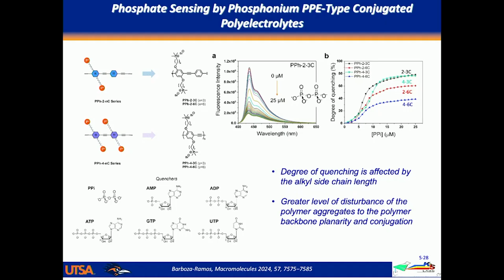So more recently, as I mentioned, one of my students has been looking at phosphate or phosphonate derivatives. Again, the polyphenylene ethynylene backbone, but now we're using these positively charged phosphate side groups or phosphonates. And he made a family of these. And as part of his work, he was also looking at what happens when you add different phosphates to this polyelectrolyte, and you see similar effects. You get aggregation induced by the interaction of the polyelectrolyte with the phosphate.